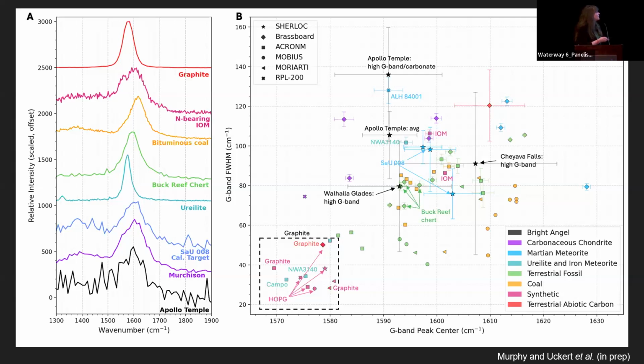And the main takeaway here is we found that all of the graphite mineral samples and any sample that had graphitized carbon within it had a relatively narrow bandwidth and plot in these lower wave numbers here. So even though our error bars are quite large on some of these Sherlock Bright Angel black stars here, they don't overlap in this area, which means it's not consistent with the mineral graphite or anything graphitized. It's some sort of amorphous carbon that we're looking at. However, it overlaps with so many different terrestrial and meteorite samples that it's hard to pull anything else out from this sample.